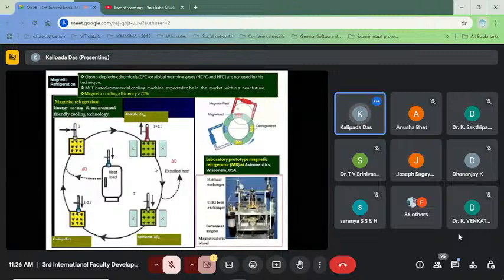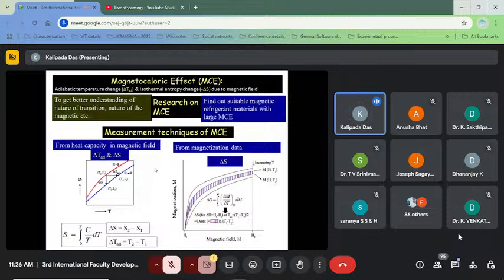Hence, the main phenomenon is the magnetocaloric entropy change, that means magnetic entropy change due to the presence of the magnetic field. So samples for which the magnetocaloric entropy change is larger will be helpful for us. Since it is associated with the magnetization or demagnetization process at different temperatures, we can easily calculate it by the Maxwell thermodynamical relation: delta S equals the integration from 0 to H of del M by del T dH.